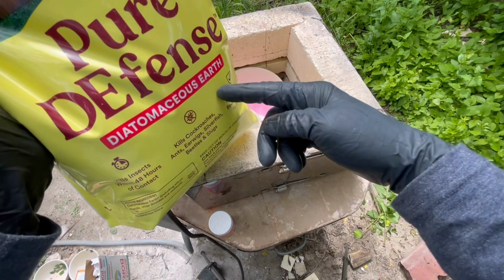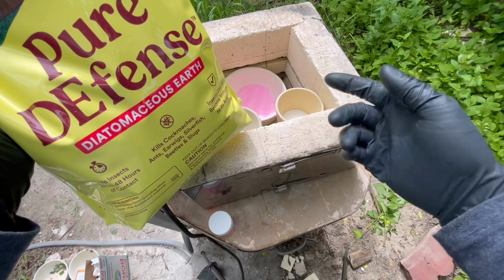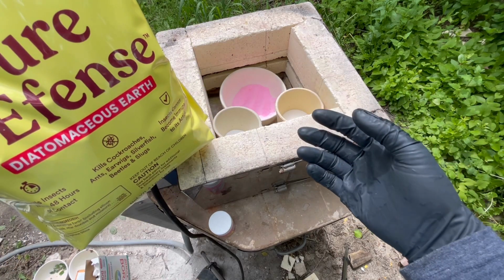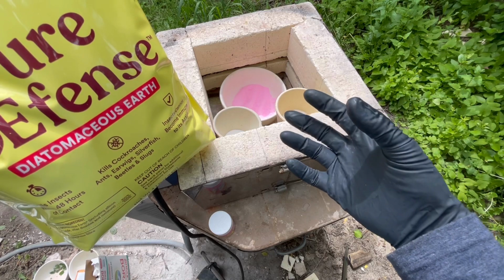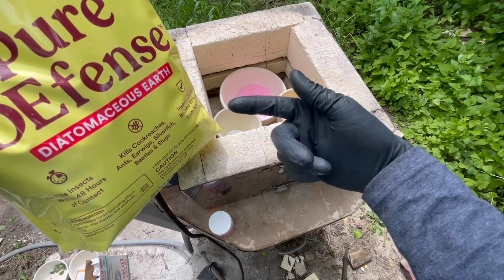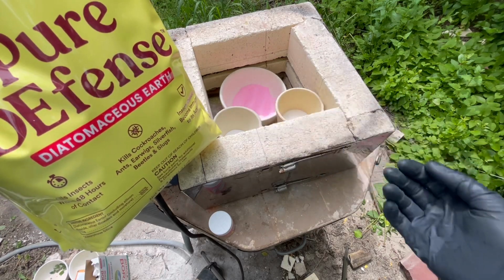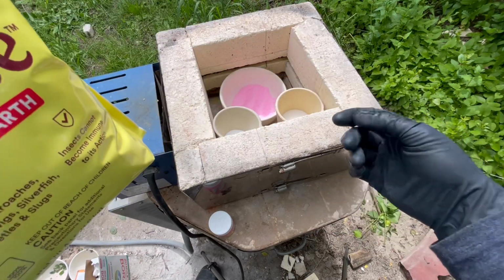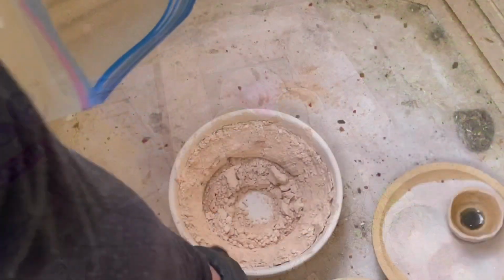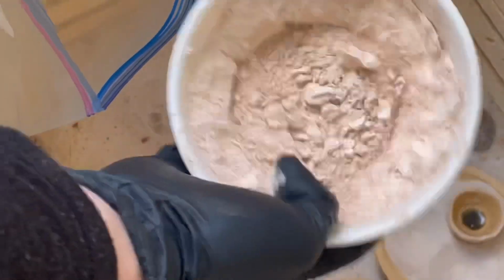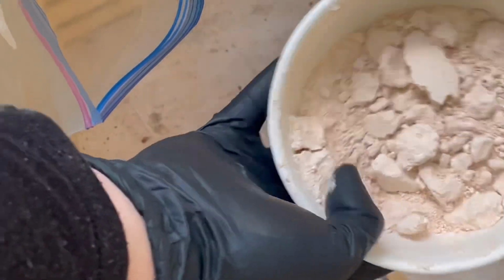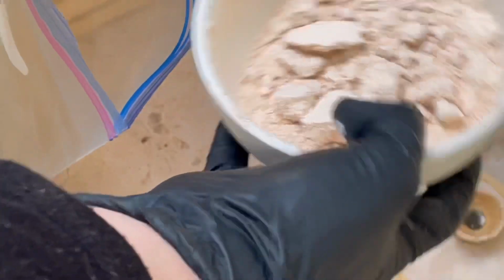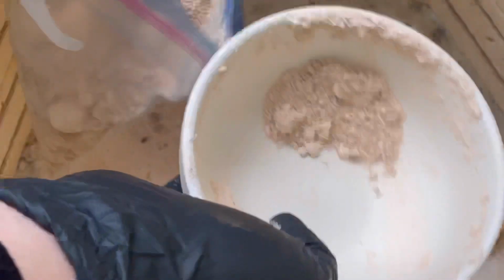This does contain a lot of water though, and just like I'm doing here, the water has to be removed, not only to prevent it from being removed later and causing a boil over, but also to make weighing more accurate, so I've not got the water weight. I do have some of this inside the furnace already. It's actually cooling down as I speak. This here that I was using to pack around one of the test samples is diatomaceous earth. It didn't get contaminated, and it's certainly dry now, so let's bag this up and use it as our silica source. You can tell that I'm filming this out of order.